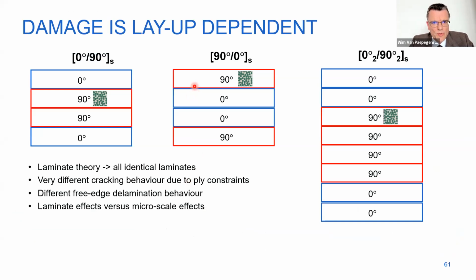For example, even if you stay at ply scale, this is for us also an important check. Can you model with your damage model these 3 layups? So you see from classical laminate plate theory, they are identical. But once there is damage, they are far from identical. Here the 90-degree ply is constrained. Here it's at the surface, and here it's much thicker. So the damage will be different. The free edge delaminations have even different signs. So this is a very powerful validation, which continuum damage mechanics models can often not take into account. So that's the first part of the answer.